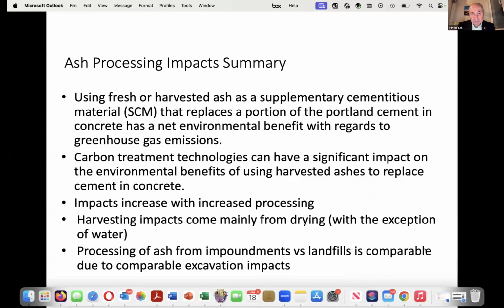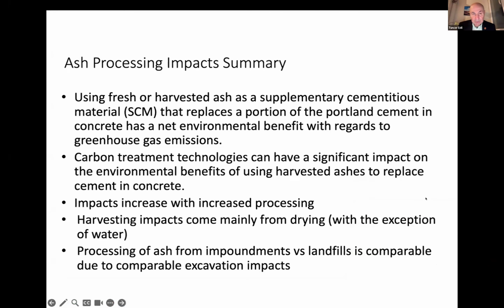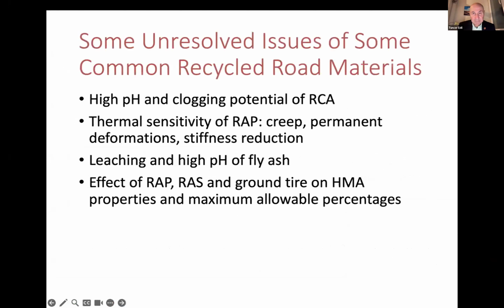Okay, I think I am at the end here. And there are some unresolved issues with some of the recycled materials. For instance, high pH and clogging potential of recycled concrete aggregate is a problem. Thermal sensitivity of RAP, it creeps and there are more permanent deformations in hot climates. Leaching and high pH of fly ash and effects of RAP, RAS, and ground tire